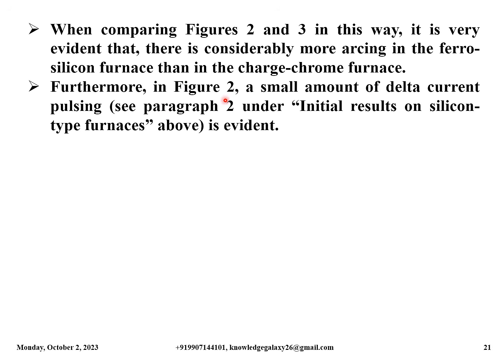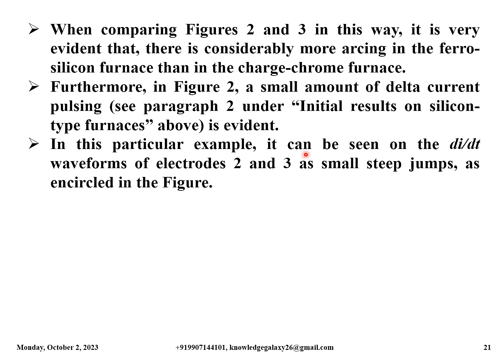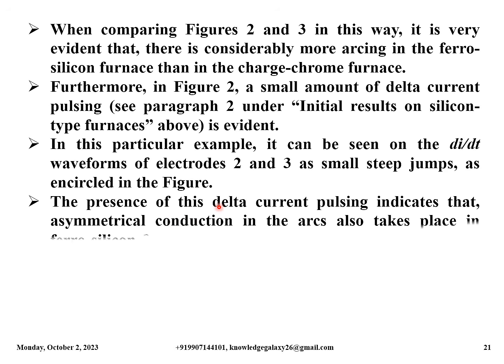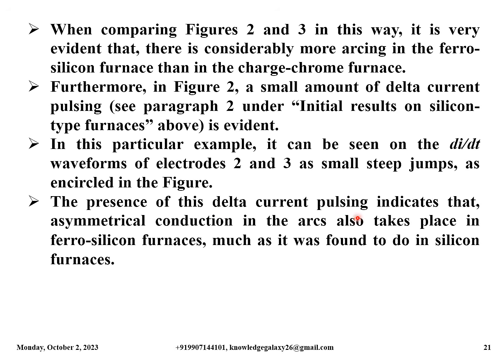Furthermore, in figure 2, a small amount of delta current pulsing is evident. In this particular example, it can be seen on the di by dt waveforms of electrode 2 and 3 as small steep jumps as encircled in the figure. The presence of this delta current pulsing indicates that asymmetrical conduction in the arcs also takes place in the ferrosilicon furnaces, much as it was found to do in the silicon furnaces.